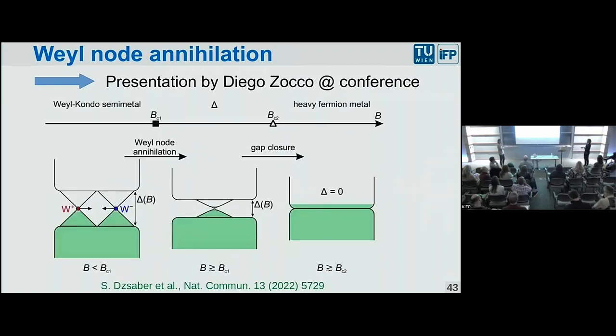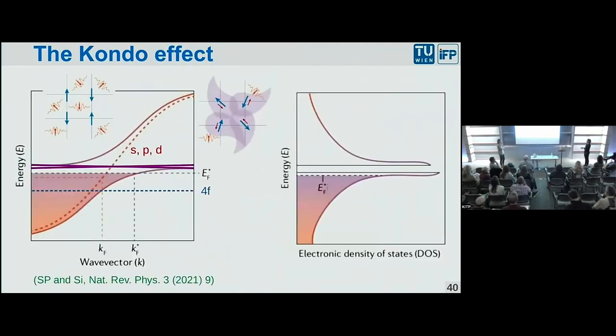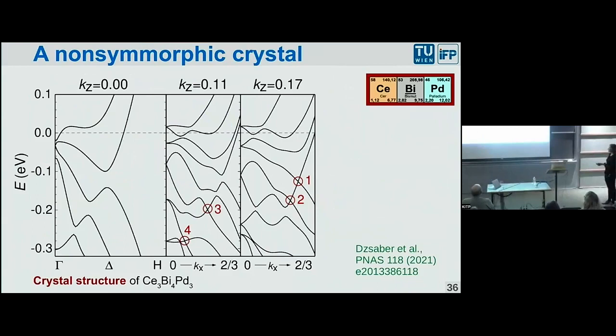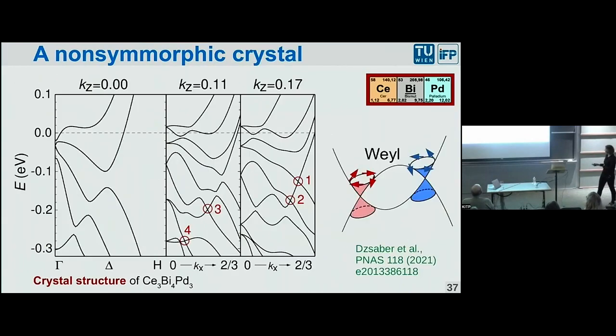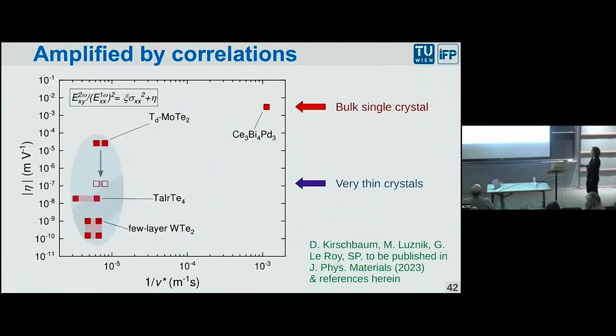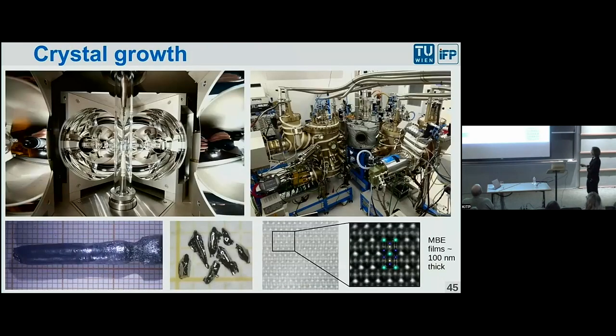No, currently we have only a material that's topologically trivial that we grow in very high quality. This is a material that is very, very interesting, but it's topologically trivial. It doesn't have the correct crystal structure. But right now in this cell, we have the cerium, the palladium, and the bismuth, and we are doing the first growth of that material in thin film form. So we are just now trying. Thank you. Yes.